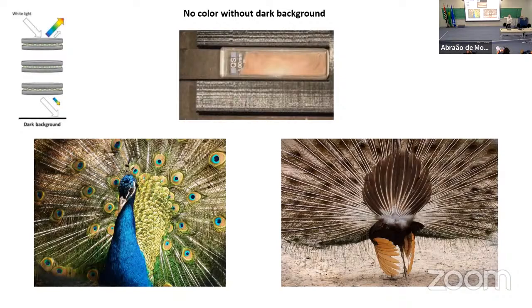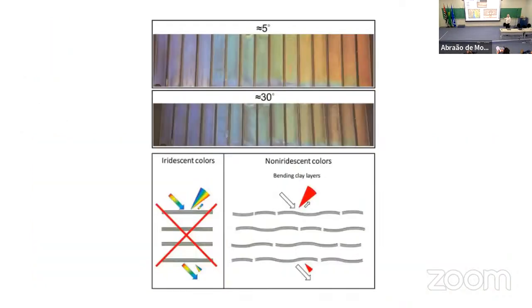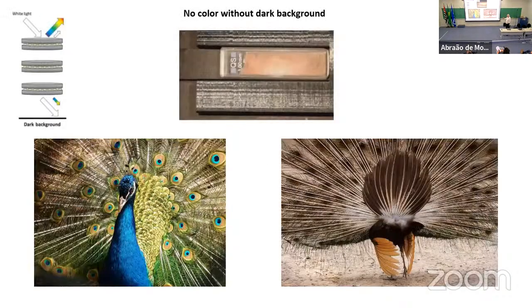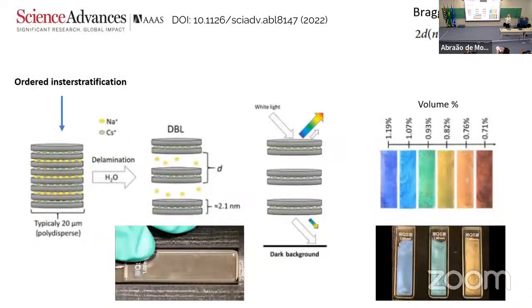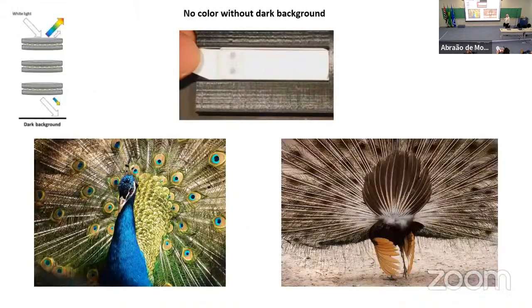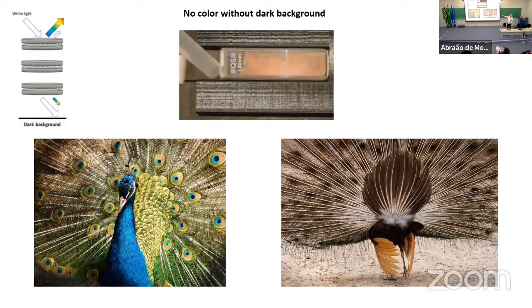If I go back to this one, one more time. You see, there's a white paper underneath. We just pull out the white paper and you see the color. If the light is reflected, you see nothing. You need to absorb the white light that goes through. Exactly the same thing has happened in the peacock.